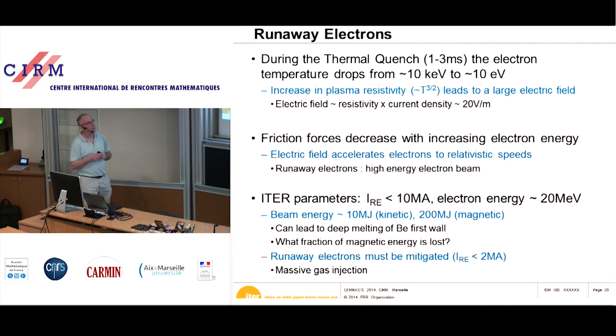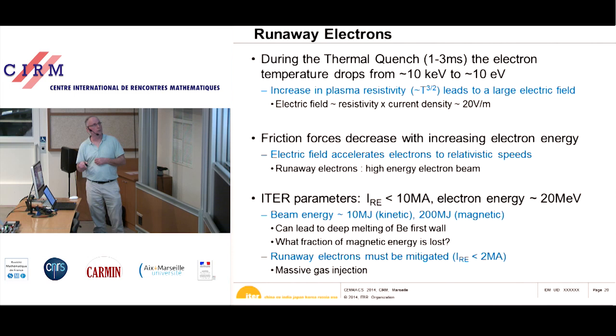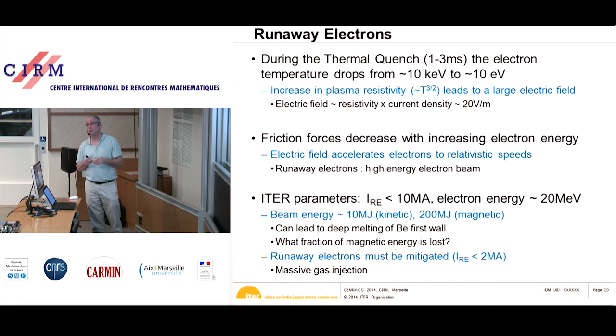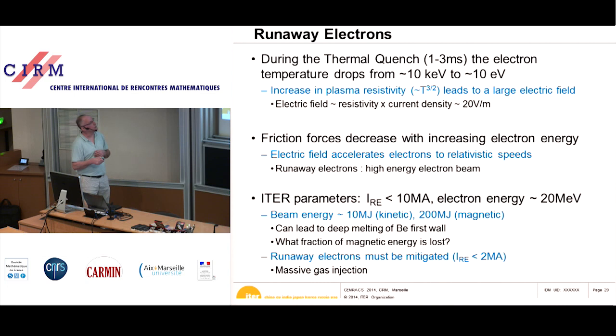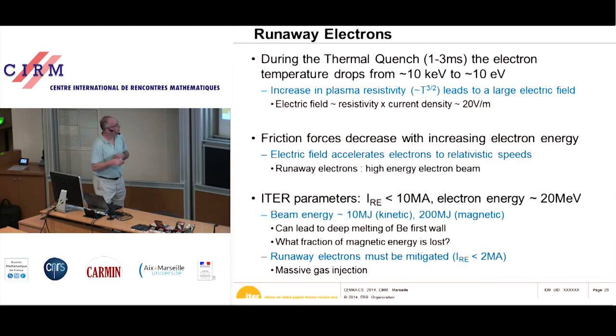The runaway beam is expected to have 10 megajoules of kinetic energy and 200 megajoules of magnetic energy. If this beam strikes the first wall — which is likely — it can cause very deep melting of the beryllium first wall. The runaway electrons must be controlled; the maximum allowable current is about 2 mega-amperes. This is also done by injecting massive amounts of gas — about 10²⁵ particles, a factor of 10 to 100 more than needed for disruption control alone.